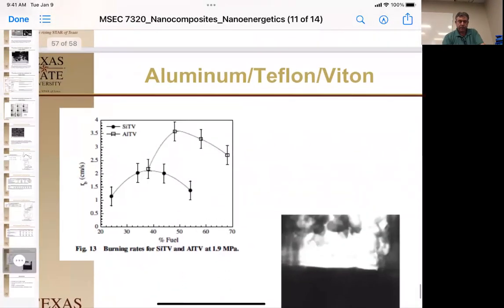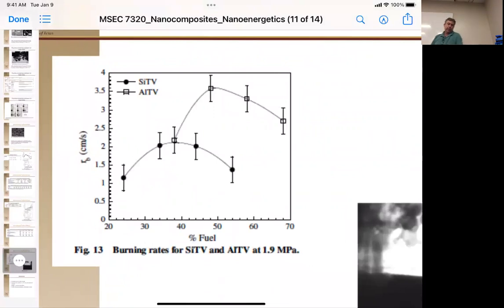Okay, and so to graph that, this is the rate of burn as a function of fuel. So this one is the silicon. It has this nice arc on it. This is the aluminum. It has the nice arc on it. So just by looking at this, you'll say, okay, at a particular burn rate here, it looks like the aluminum material burns faster and hotter than the silicon-based material. And you have a maximum you want to use on both of those different materials.